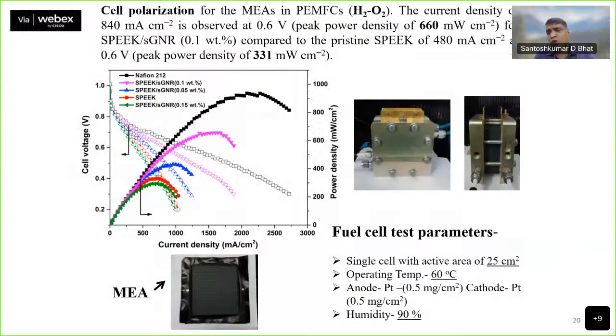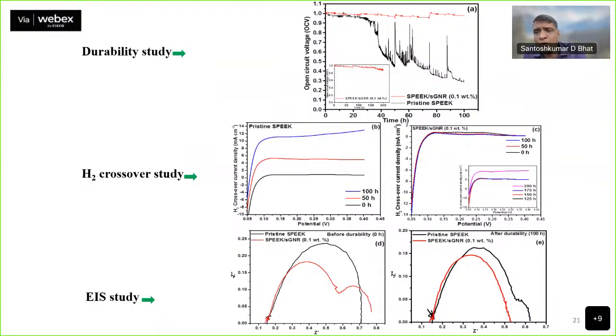So we do the cell, we don't stop there. We do the overall cell testing. So single cell polarization is very, very important. So we do testing in a single cell, and then we do IV characteristics. So this is the cell assembly where we see the comparison. When we do this indigenous membrane, we always compare with the state-of-the-art commercial membranes. So we compared here with Nafion 212 membranes, where we can see that the indigenous membrane is reaching the stage where Nafion 212 is, and we believe that with further improvement, this can be even on par with the commercially available membrane.